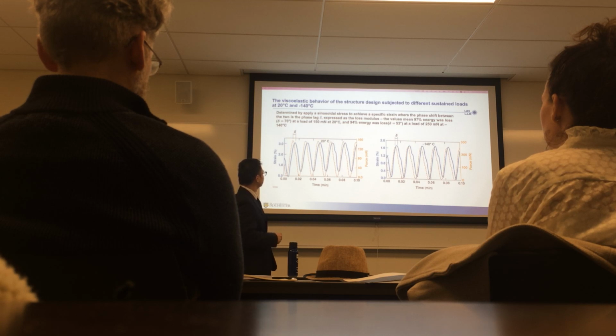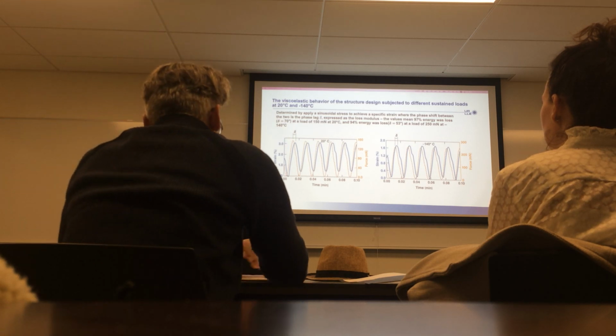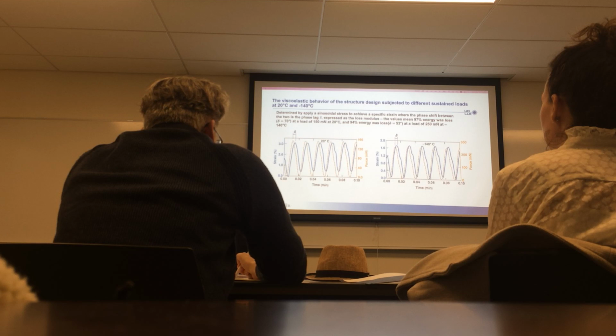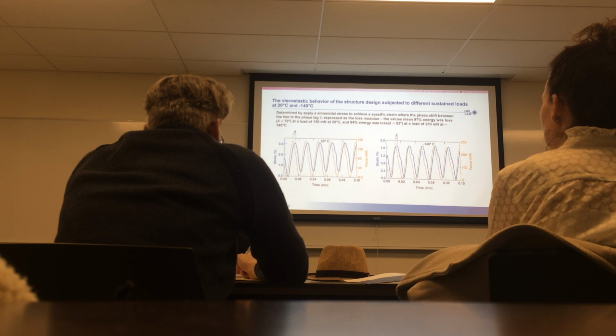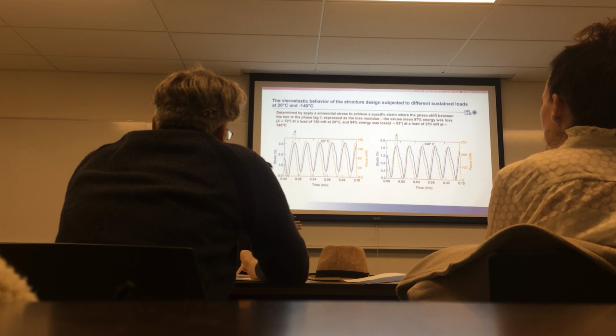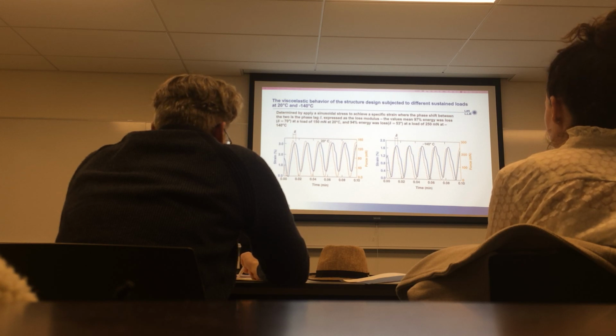And we found that at room temperature, this foam structure's energy loss reached 97%. And even at cryogenic temperature, the energy loss is still 94%, which means most of the energy was dissipated during the compression. That's a very good result for a foam structure to dissipate energy.